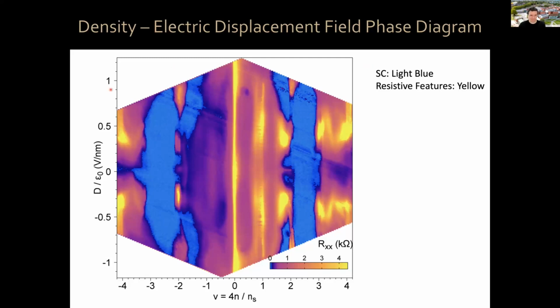Now, I want to point out to you that this phase diagram, if you look from 0, top half and bottom half, is largely symmetric. You can even see these features like this, which are also top and bottom symmetric in displacement field, these branches, etc. Now, electron doping and hole doping from charge neutrality, so left and right, there is some degree of symmetry, although it is less symmetric. But you can see there is also a degree of symmetry, including these branches, etc.